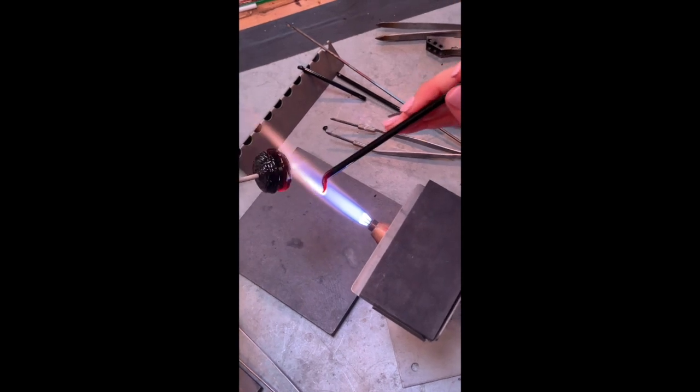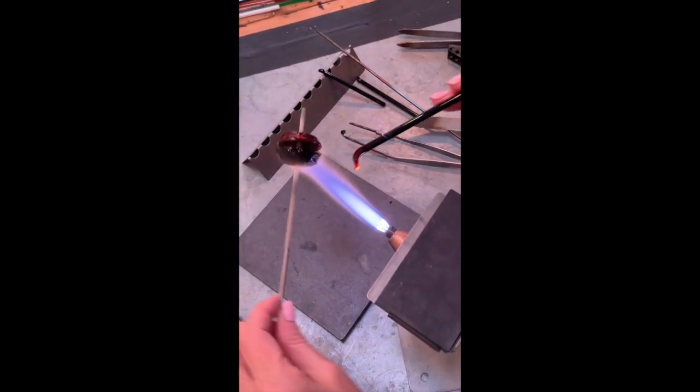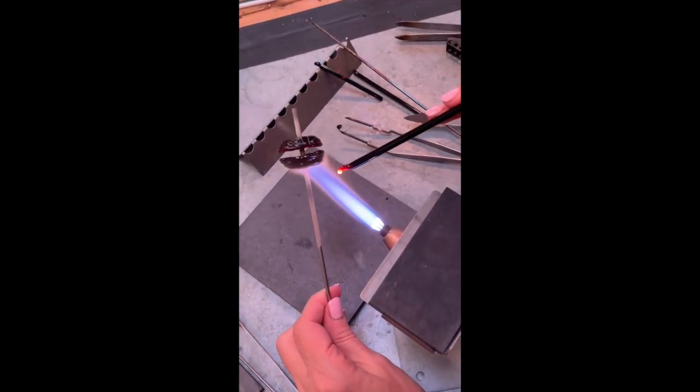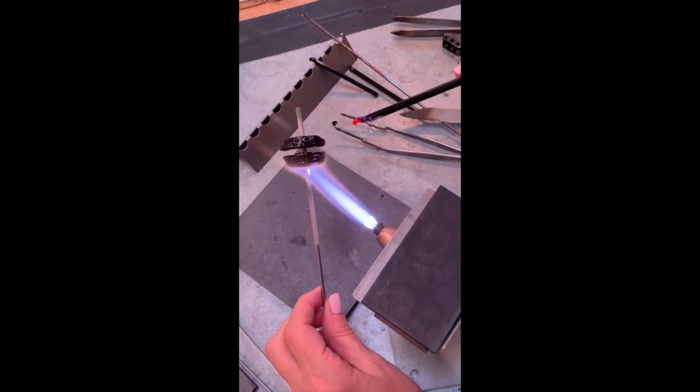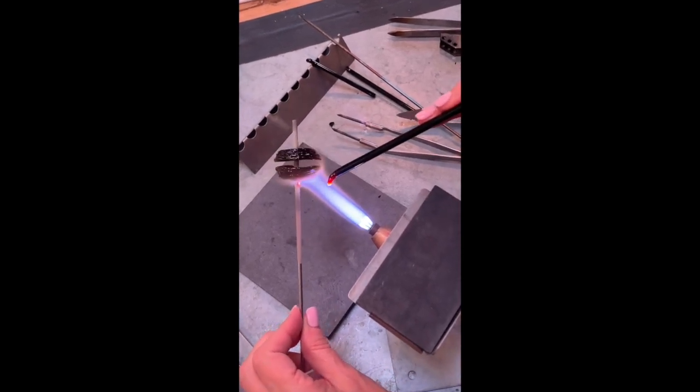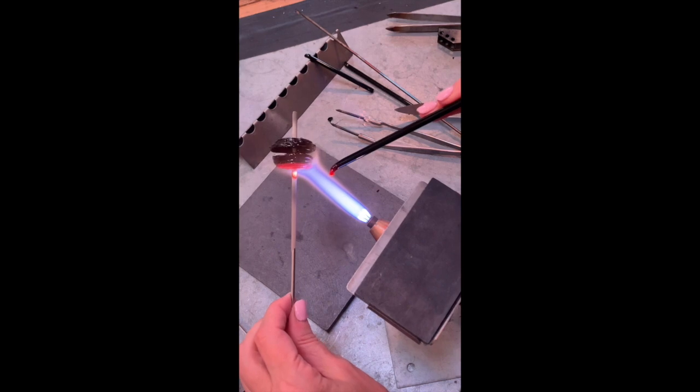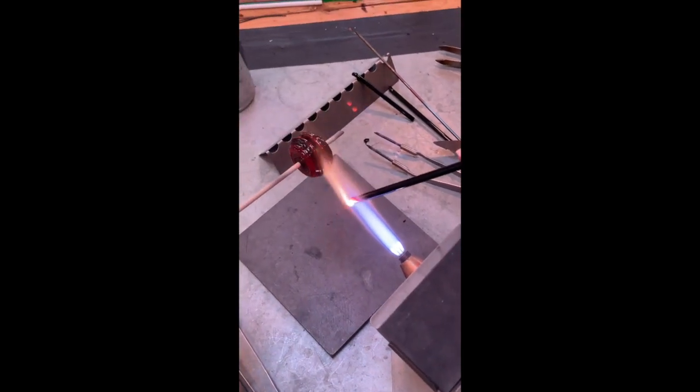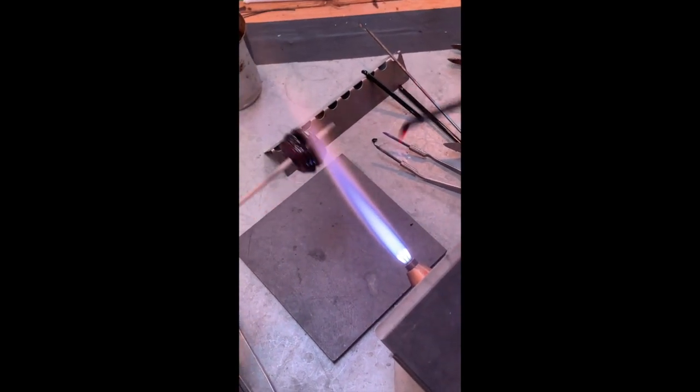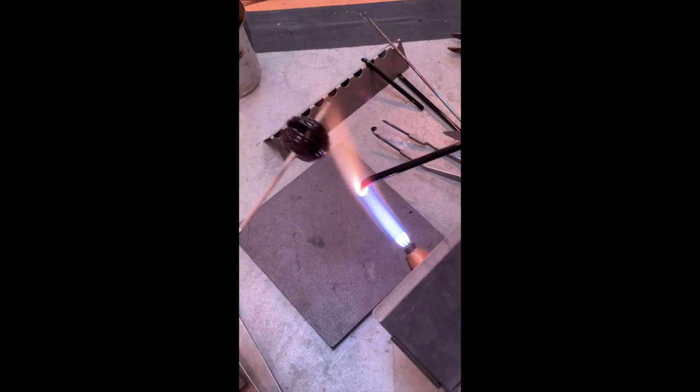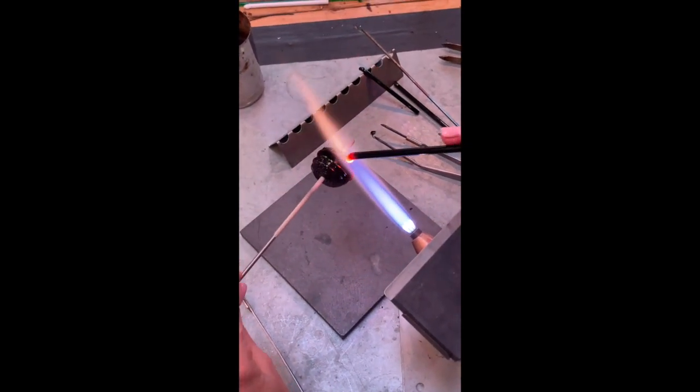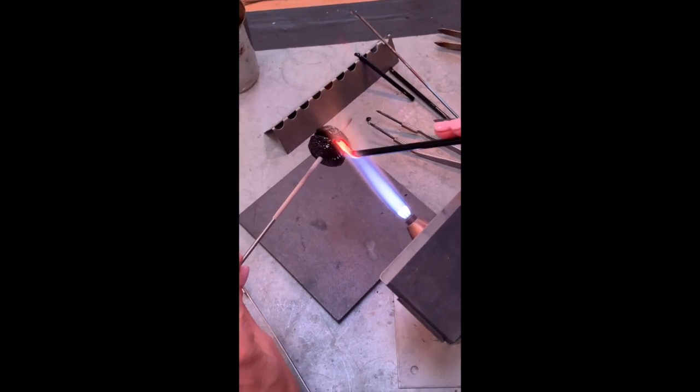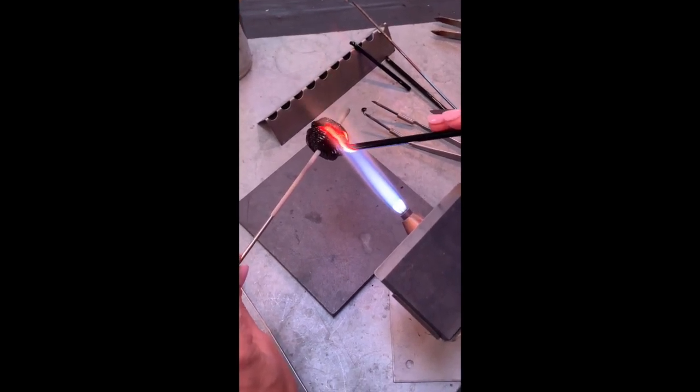And by that I mean heating the rim of the disc where you are about to add glass will give you a hotter connection and enable your wraps to be in full contact, not giving you that little inchworm that people complain about. I doubt that's the sound of an inchworm. So, talking so much, my wraps are not as lovely as perhaps I'd like them to be.